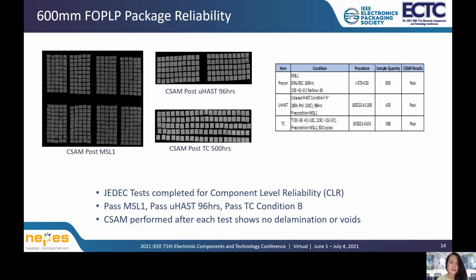The test vehicle was then subjected to component level reliability tests such as MSL1, unbiased HAST 96 hours, and temp cycle condition B. CSAM was performed after each test to ensure no delamination or voids occurred. Inline data for thin film processing through solder ball attach were collected, such as critical dimensions for passivation layer 1, RDL, passivation layer 2, and UBM.